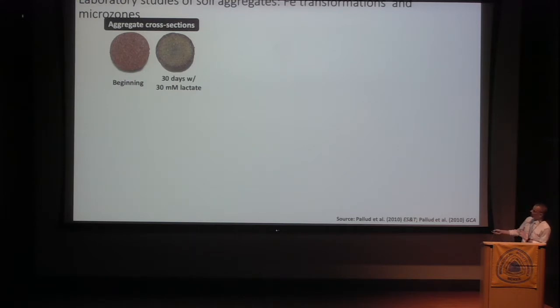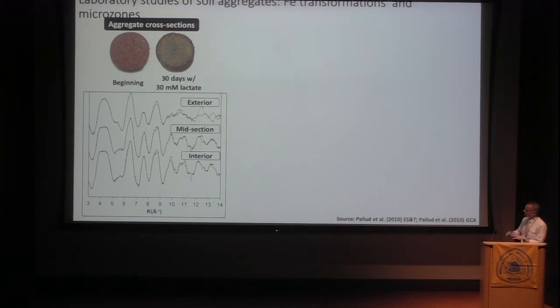Showing a cross-section through the soil aggregate, and then after 30 days, clearly showing a change in the mineralogy of this material. And these were studies that were done to try to mimic what's actually happening in natural soil aggregates with fewer variables. They could track over time and over space the mineralogy of the iron-bearing phase, showing changes from the interior to the exterior with the corresponding color change.